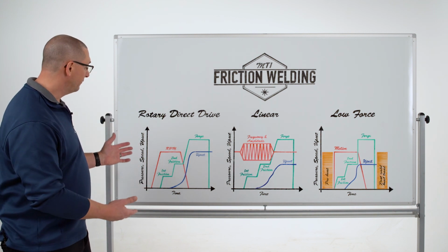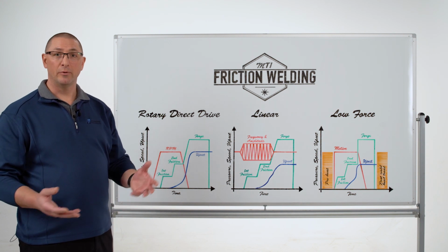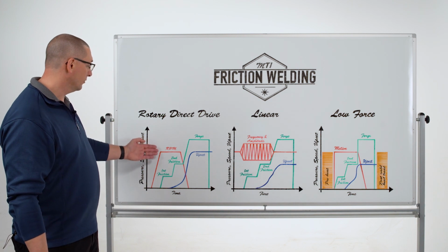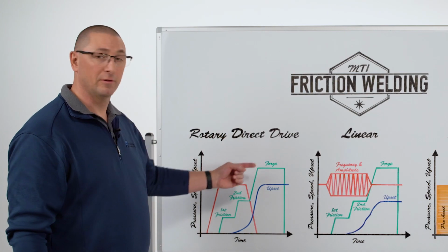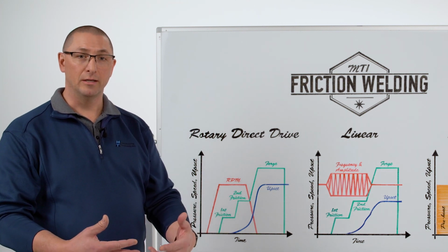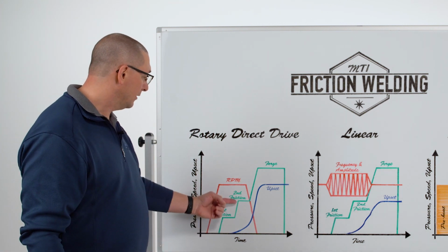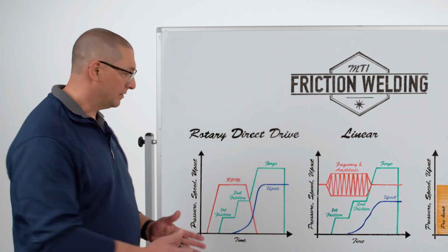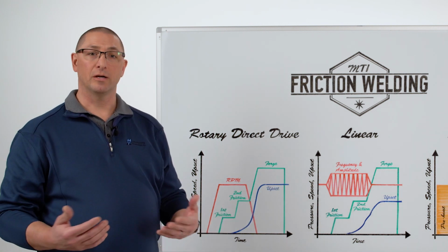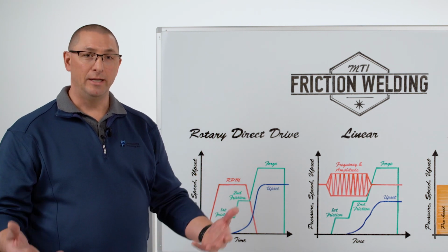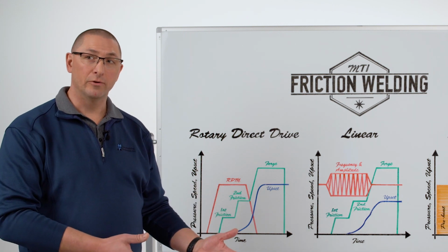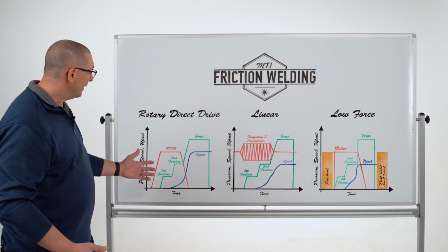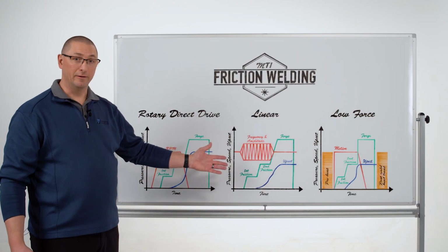If you recall, in direct drive friction welding, we're attaching a round component on the spindle side and a stationary component on the tailstock side. We rotate it up to a certain speed, and then we bring on a different load profile in order to get the energy in to make the weld. My second load allows me to get some upsetting, and then I squeeze out all the hot material in the forge phase. I can extend this second friction phase where I'm getting upset in order to add more heat to the component so that I can control the cooling rate of it and not form martensite for a hardenable material. I can take that same thought process and apply it to linear friction welding.